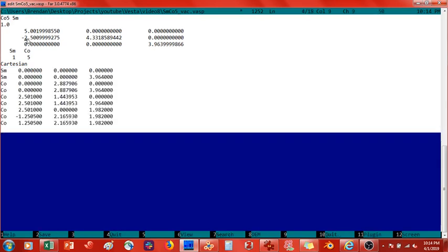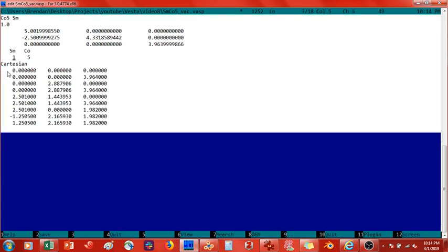If you can see here, actually between the A and B axis, we do have this angle. If it was between the A and C, the number would be down here. So we have 2 samarium atoms and 1, 2, 3, 4, 5, 6, 7 cobalt. So let's just change these: 2 samarium, 7 cobalt. The first 2 will be samarium, and the remaining 7 atoms will be cobalt. And then we are going to add 10 angstroms of vacuum in the C dimension.